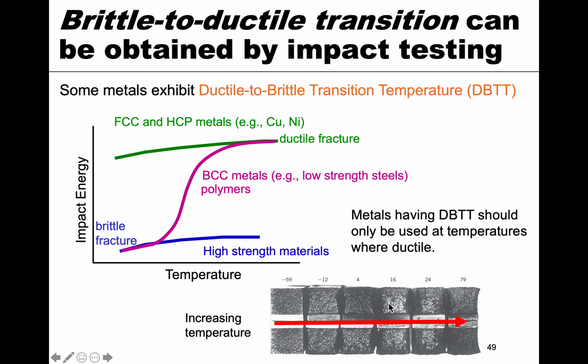And then as you go lower, you'll notice that it becomes smoother and more square, right? And it follows the shape that it was before. So it doesn't have that plastic deformation like these higher temperatures do. And so that's where we kind of follow this temperature. So this negative 59 is down here, and this 79 is up here, and then you have a transition in between. So that can be measured by taking impact testing at different temperatures for a sample. And this is obviously something that's important, not only for brittle materials, but for materials that can become brittle with temperature. So that's something else to consider when we're talking about measuring fracture toughness.